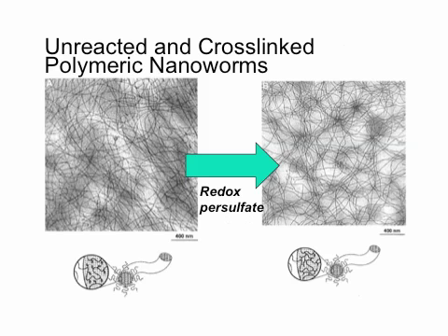So what do you get? Well, here's what it looks like under a TEM image. You have these wormy structures, and you can imagine that the viscosity of this system will be very high. And obviously, if you've glued it all together, you might even have a permanent gel. Because in this case on the left, you can exchange, right? Things can move, which means you can break up, so your cylinders can snap and make another one. And on the right-hand side, when it's all glued together, the only way you can break a cylinder is to literally break the covalent bonds, which happens under very high shear, but you know.